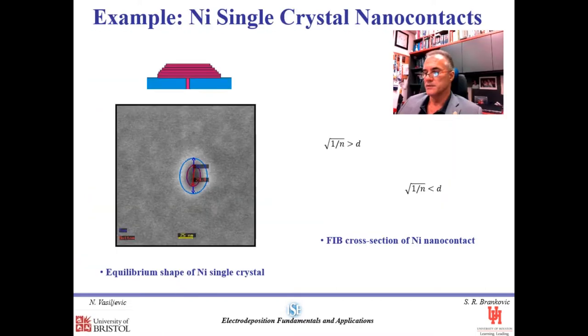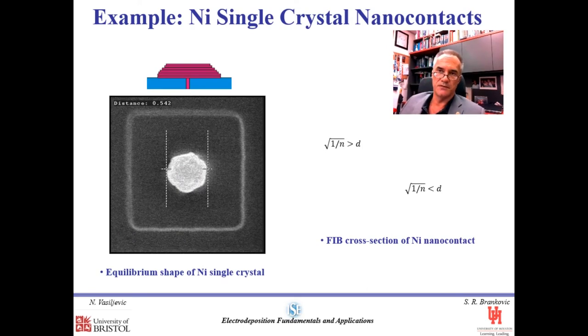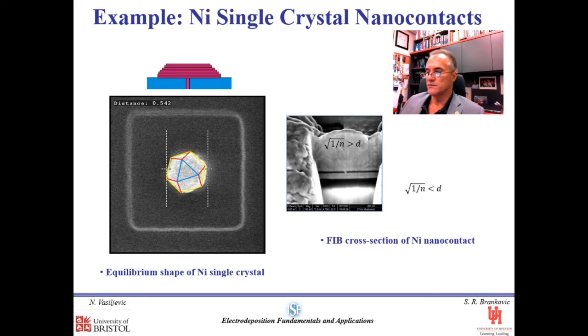To give you an example here, this is a photoresist nanoelectrode structure which is of the order of several tens of nanometers, and depending on how you run your process, if you adjust your current density or the deposition flux, this relation is valid. Then what happens is that you generate only one nucleus in this confinement, and you have a single crystal deposit within this nano-confined electrode geometry. This is also evident when the deposit mushrooms on top of the photoresist, then the shape of the deposit starts to take the shape of a cube octahedron, which is the equilibrium shape of a single crystal for FCC metals, such as nickel, for example, here.